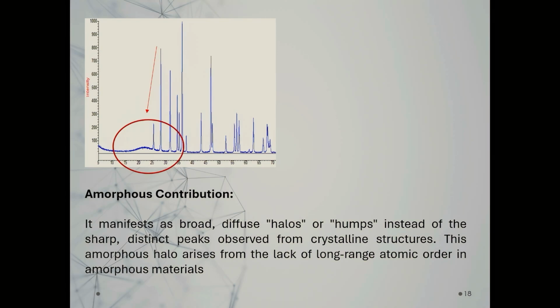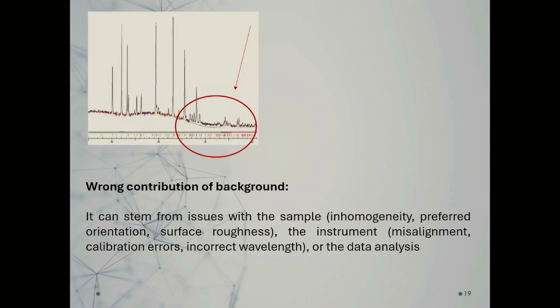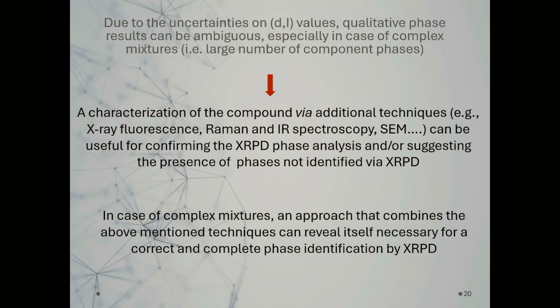When we have the presence of amorphous material, it's quite difficult to understand if under that hill we also have a peak that contributes to having a phase inside the sample. And also the wrong contribution of the background. When we calculate the background, we can make an error. So due to all these problems connected with powder diffraction, when we have a complex mixture we advise adding other additional techniques to assess what we have obtained with a qualitative phase analysis. We can also add data from X-ray fluorescence, Raman, IR, SEM, and so on.